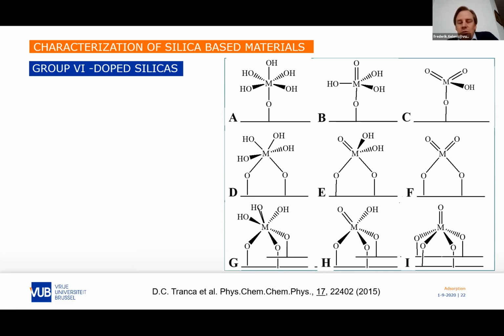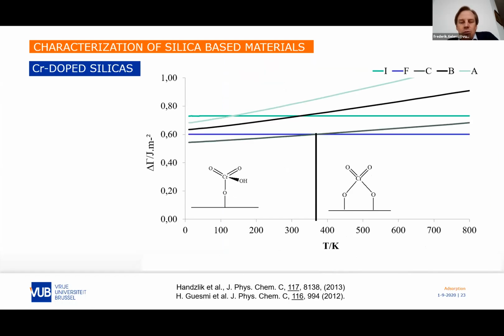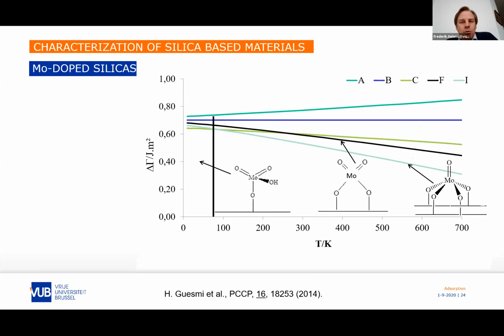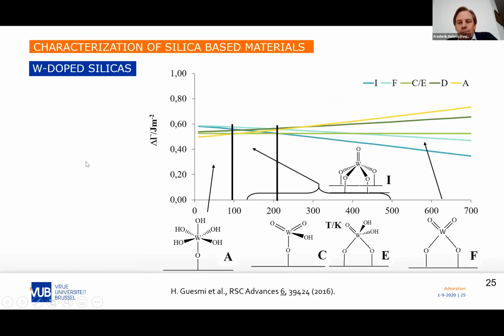We did this for the 3 elements in group 6. So we did this for chromium. Here it's quite a simple one. You have a hydroxyl group here, the mono-oxo with 1 link, 2 links, the dioxo, which is very famous in reactivity, like the Phillips catalyst, which is used for polyethylene synthesis. We went down the table, from chromium to molybdenum, so we increase even more the complexity because there are more types of systems that appear, and for tungsten we have even more complex systems, yes? But we were able to define the domains of stability.